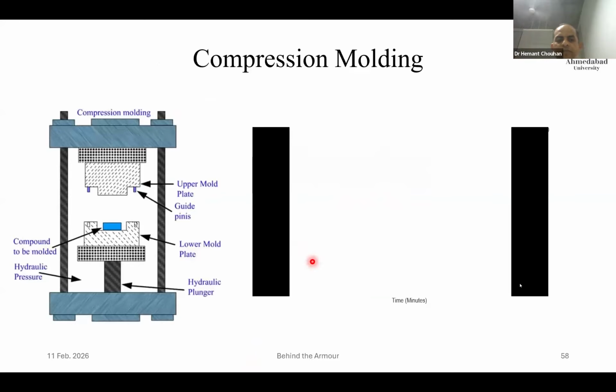Now, how do we manufacture a laminate out of it? For UHMWPE or for the composite part of it, compression molding turns out to be the best possible option. Compression molding is a standard process wherein we place the desired number of layers inside a lower platen, which is a hot surface, and there is an upper platen as well which is also hot at the desired temperature, let's say 100 degrees or 130 degrees depending on the polymer properties or the matrix material. We close this, apply the rated pressure for a designated time along with the vacuum, and cure it.